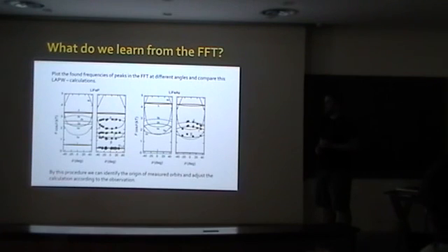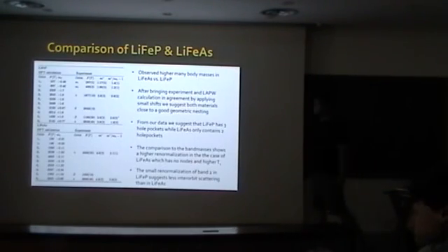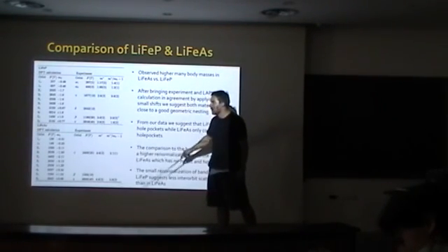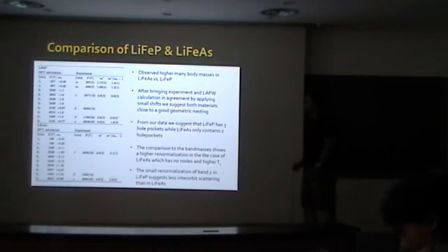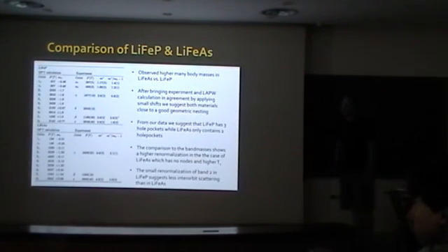You mentioned also that you wanted to see the change of the effective mass in the superconducting state. What we see is that as Tc grows, this renormalization factor is higher, and this explains the higher critical temperature of lithium iron arsenide compared to lithium iron phosphide. But you could only see quantum oscillations in the superconducting state if there were Fermi surfaces that do not take part in the induced superconductivity. Sometimes you are lucky enough that you can see that. So I think we need to